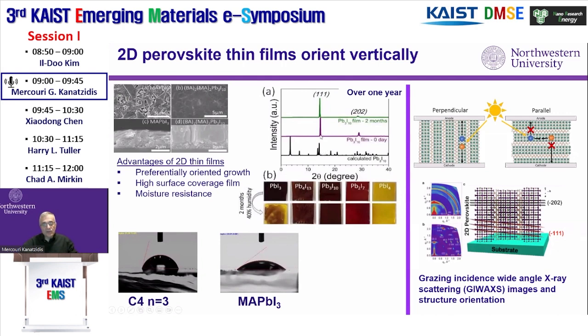And the reason for that is it was very strong orientation. This is a butylammonium. Very strong orientation where the layers are perpendicular to the substrate. And the second remarkable finding was that after months, even a year, it didn't change. And that's remarkable because if this was a 3D film, it would have decomposed. And one of the reasons for the stability is that these are more hydrophobic because they have these long chains. So the contact angle here is higher, for example, than here, which is the 3D material. So, okay, that makes sense. But also, the ion migration is slowed down significantly, maybe by orders of magnitude, in the 2D compared to the 3D. And that also contributes to the stability.